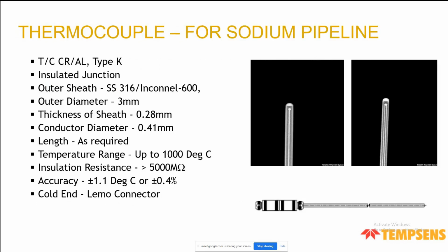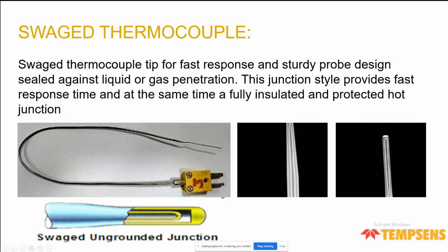Then we supplied to the PFBR reactor in India at South Bhavini. These were used in the sodium pipelines. We supplied the heaters also for these pipelines. So these were temperature sensors, 3 mm diameter, type K and type N. Both we supplied. Outer sheath of 316 and Inconel, rated for 1000 degrees centigrade, more than 5000 megaohm, with class 1 accuracy, and with the LEMO connector. There were a lot of requirements, like we had to do radiography and other tests for this customer. They were again as per ASTM E235, the mineral insulated cable for this.